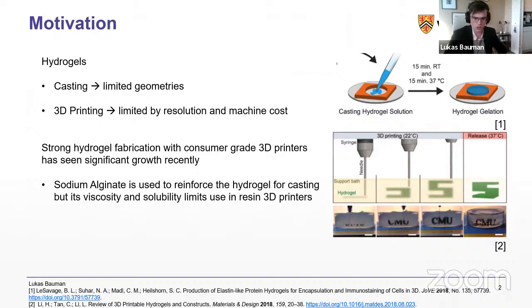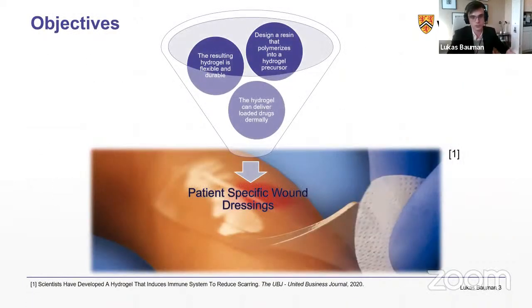And recently we've seen a lot of improvements in resin-based 3D printers over the last 10, 15 years, and also a significant decrease in cost. So what we wanted to do is make a smart resin using sodium alginate as a reinforcement that you could make as a resin and print on a lot of consumer grade printers. So all you had to do is provide someone with this resin and they could make smart wound dressings, which is what this comes to, patient-specific wound dressings.